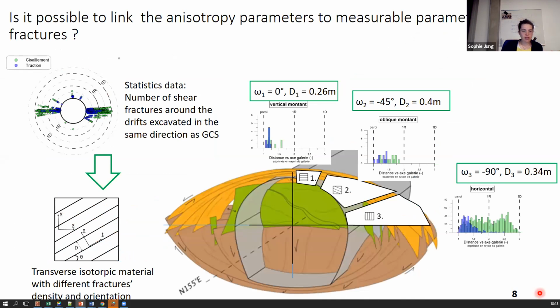So since our idea is to consider that the observed anisotropic behavior is due to the fractures, we were wondering if we can properly link the behavior of the fractures to the parameters of anisotropy. So now the idea is to formulate with homogenization technique the elastoviscoplastic behavior of one representative elementary volume constituted by isotropic sound rock crossed by equidistant parallel fracture planes, and then describe the fractured zone by such REV.